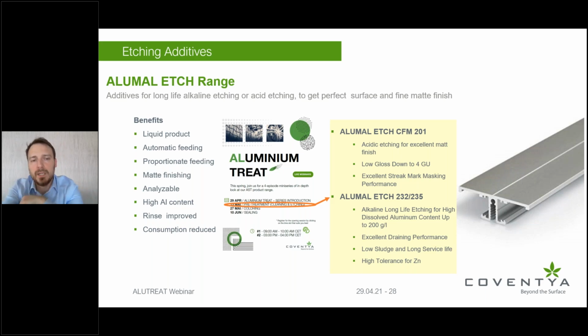So this chemistry is one of the key elements for a successful aesthetical look, especially on different alloys, based on their components or constituents. This subject will be covered extensively again on the 12th of May in our special webinar series by Mr. Alson, where currently we are also combining the acid etch with a post-caustic etch step. This gives us the opportunity to have, if we want, a very low gloss, up to 4, surface appearance without streak marking, which is an extremely useful tool.